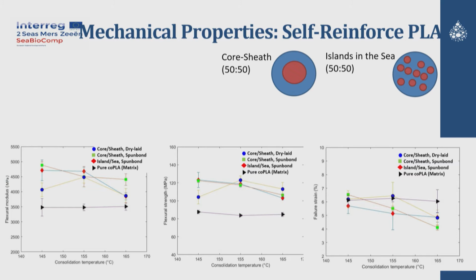You can see the results according to the temperature: the flexural modulus on the left graph, the flexural strength on the middle graph, and on the right, the failure strain. In general, there is a common issue in material science that we cannot enhance stiffness, strength and toughness, ductility at the same time. It is very difficult. But anyhow, you can see that we could increase stiffness and strength without compromising ductility. So it is very good news.